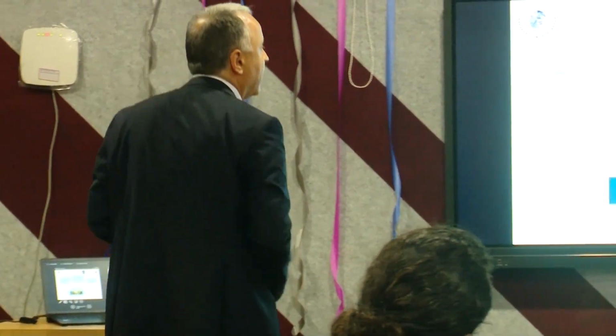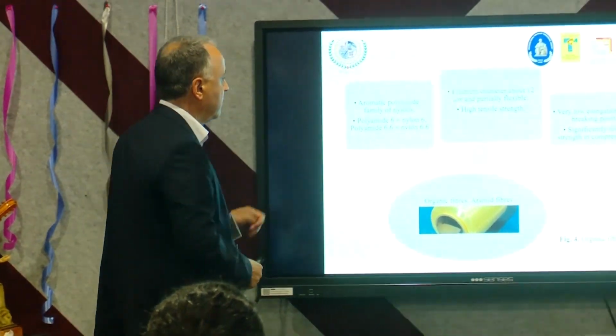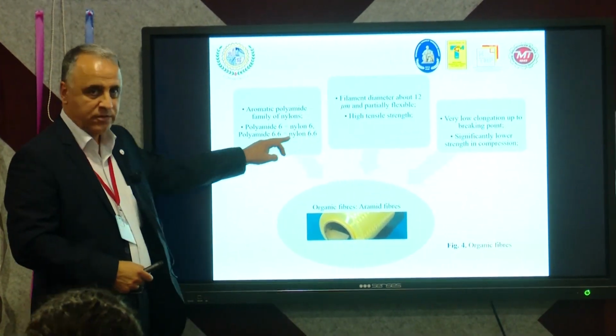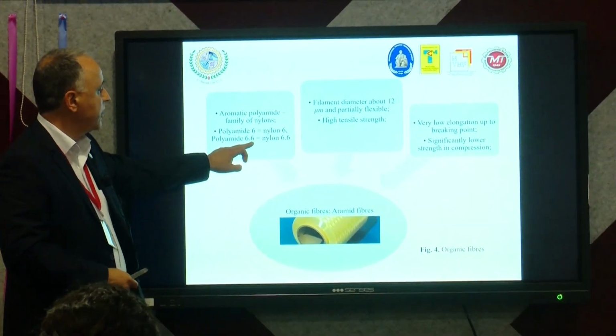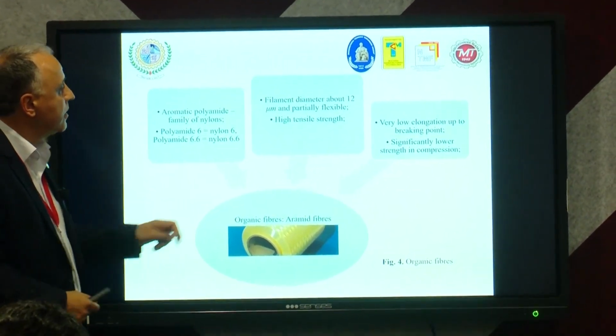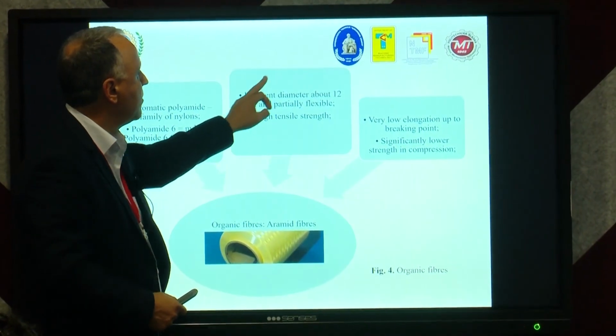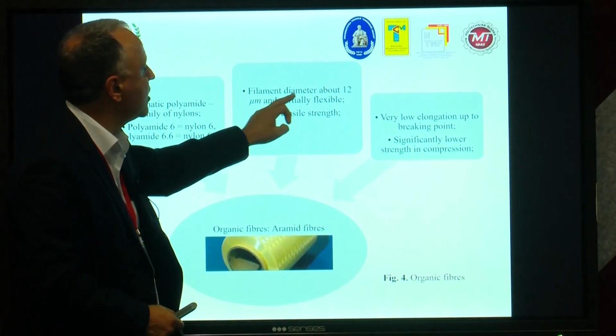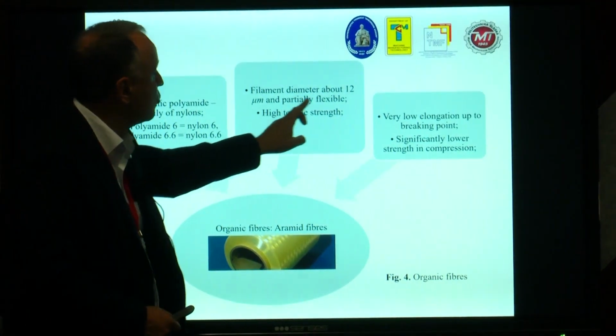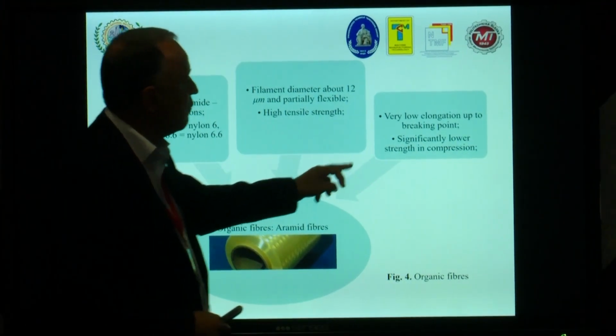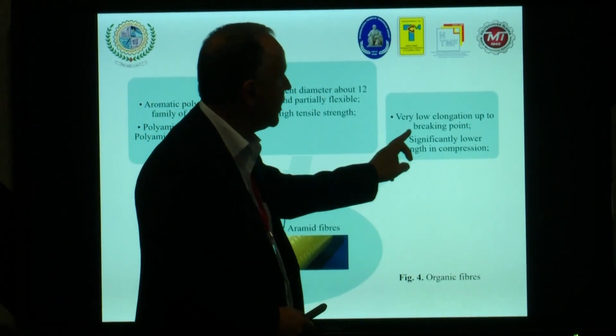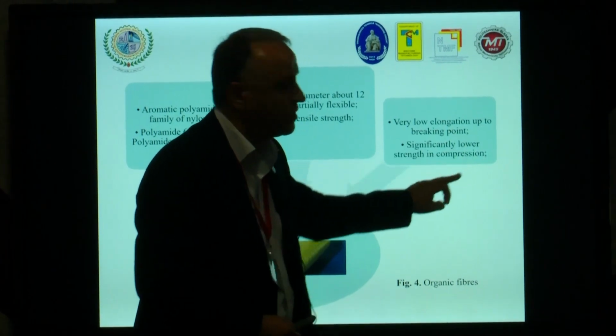Organic fibers. Aromatic polyamide, family of nylons. Polyamide 6, nylon 6. Polyamide 6.6, nylon 6.6. The diameter of the filament is about 12 micrometers and partially flexible, but with high tensile strength, very low elongation up to the breaking point, and significantly lower strength in compression.